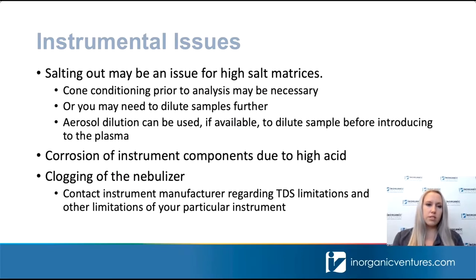Now I want to discuss just some general instrumental issues that you may see when conducting these types of analyses. The matrices for these complex samples are going to be complex matrices, and therefore you may have some issues with salting out. So one option for accounting for this is cone conditioning. So just running your matrix for a prolonged period of time before conducting your analysis to make sure that the cone is conditioned with that salt matrix. Another option is to dilute the samples so that this doesn't occur. You could even do an aerosol dilution to make sure that the sample is more dilute before entering the plasma.